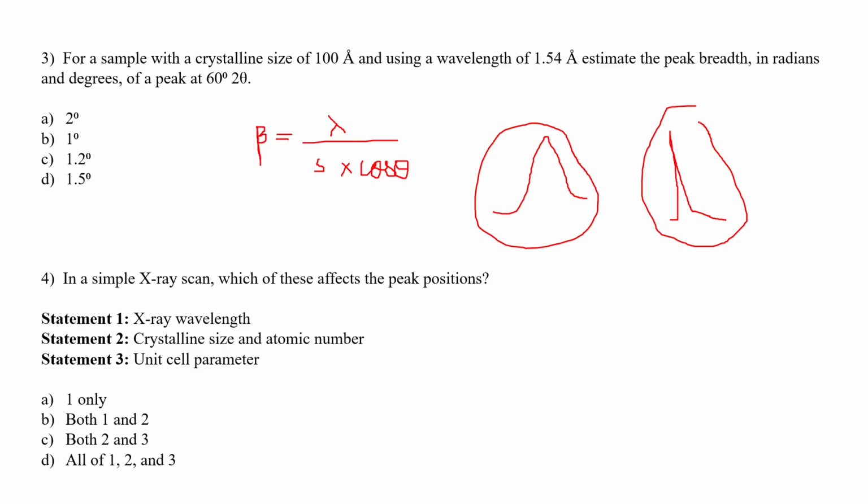So depending upon the FWHM only, this FWHM is the full width half maxima, this value is very high for nanomaterials and very low for bulk specimens. So this is basically given by this Scherrer formula, and there is a proper calculation you can do, from where you can find out what will be your crystal size depending upon the FWHM of your peaks.